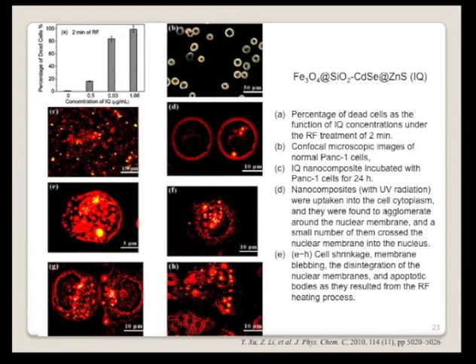Let's see the different concentrations that were added into the medium during the incubation of the pancreatic cells. Without the nanoparticle, just turning on the RF heating for 2 minutes doesn't kill many of the pancreatic cells. But when you increase the nanocomposite, you can see the death percentage of the pancreatic cells increases with concentration.